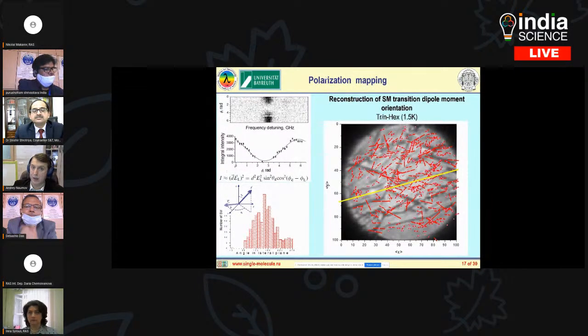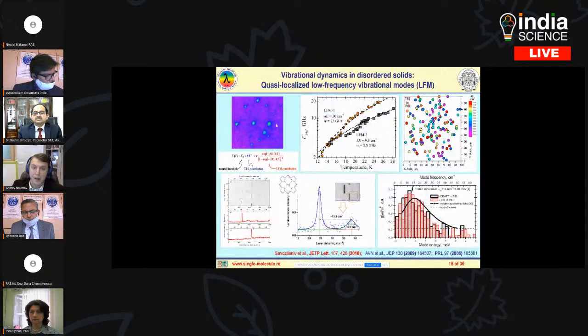For example, I can realize polarization mapping. For each molecule, I can find the orientation of this molecule in space. And then I can see how my label molecules are oriented in the sample. I can realize some kind of vibrational microscopy, because for each molecule, I can measure the temperature dependence. And when I analyze this temperature dependence of the spectrum, I can find the energy of vibration in my solid film. And then I can map these vibrational parameters in space.